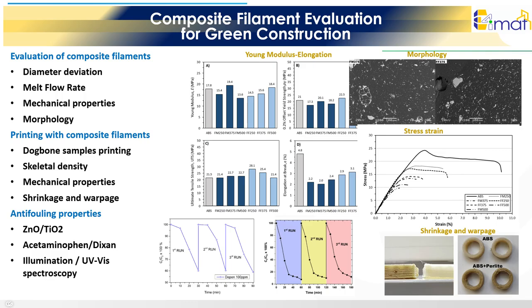A full evaluation was performed to validate the composite filament as a sustainable construction material. We examined physical and mechanical properties, particle dispersion, morphology, and printability. In addition, 3D printed items were tested upon the degradation of organic pollutants, e.g. pharmaceuticals, detergents, etc. The results confirmed that the composite supports stable extrusion, low density, and robust performance, key characteristics that enable reduced material consumption, lighter building components, and improved environmental performance.